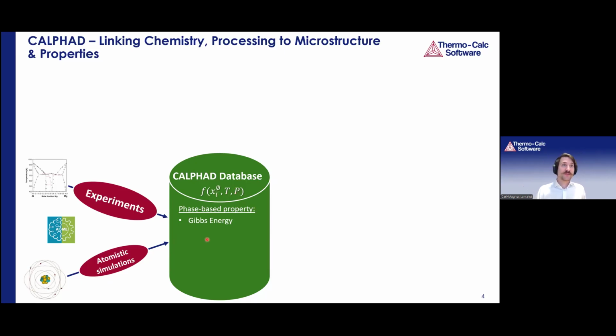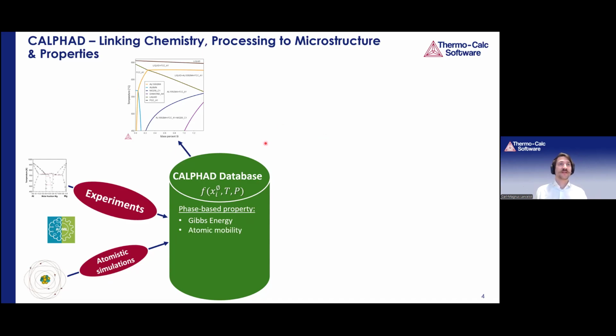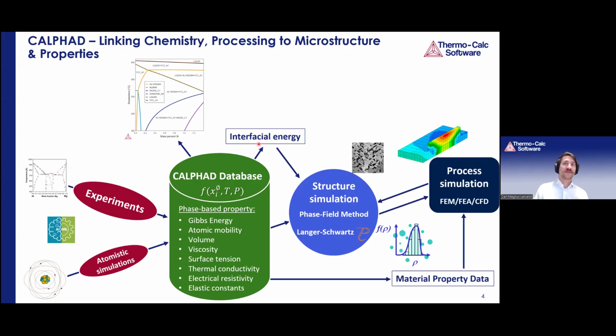And the properties are the Gibbs energy, which can be used to derive all kinds of different thermodynamic properties, and also the phase equilibria, so we can calculate phase diagrams, and also atomic mobility, so we can simulate the kinetics of phase transformations, and also some thermophysical properties such as molar volume and the viscosity and the surface tension of the liquid phase, the melt, the thermal conductivity and the electrical resistivity of the alloys. And we're currently working more and more on introducing elastic properties into the databases.